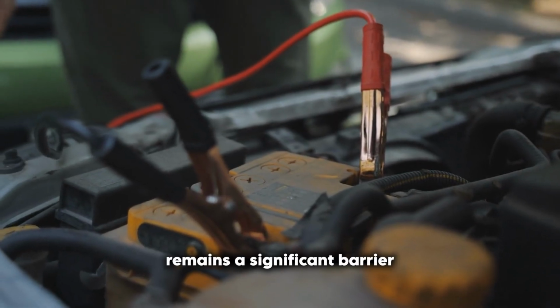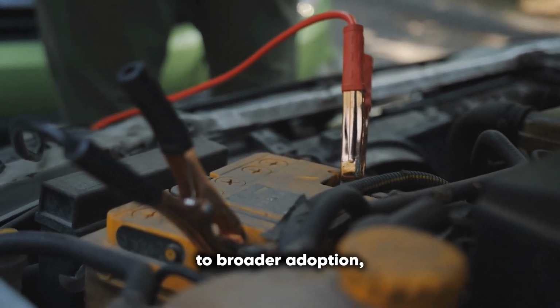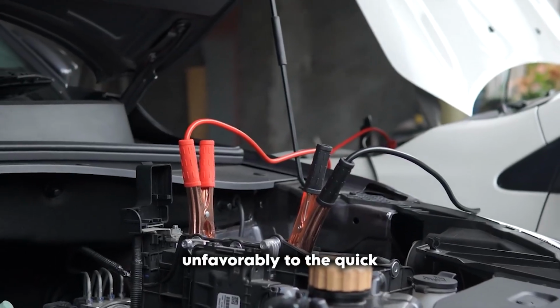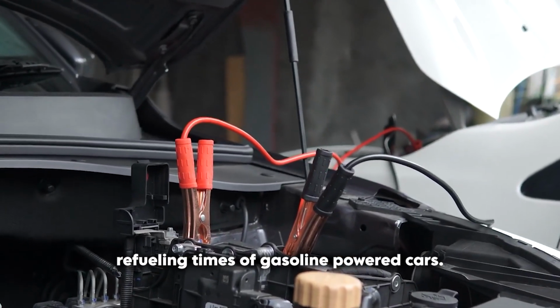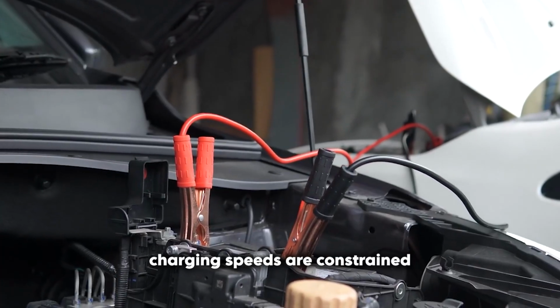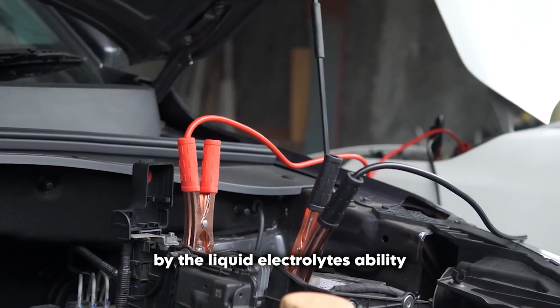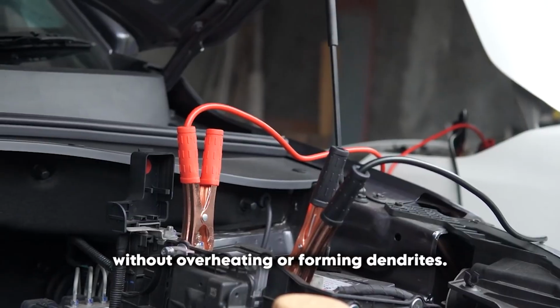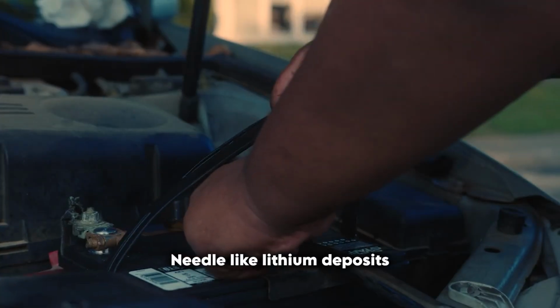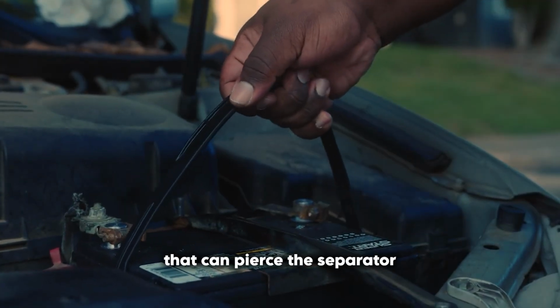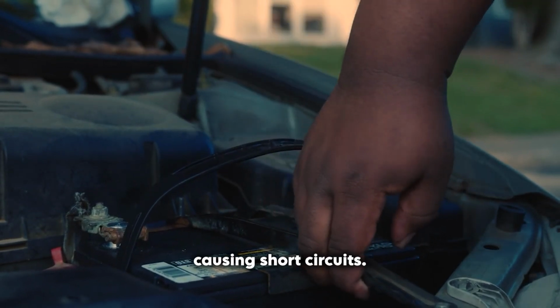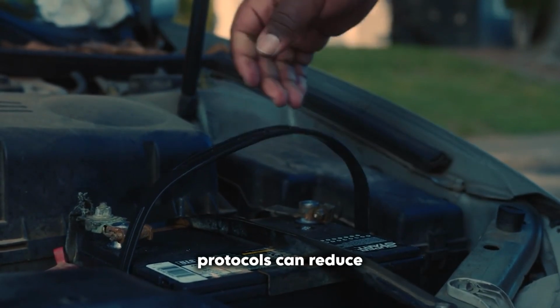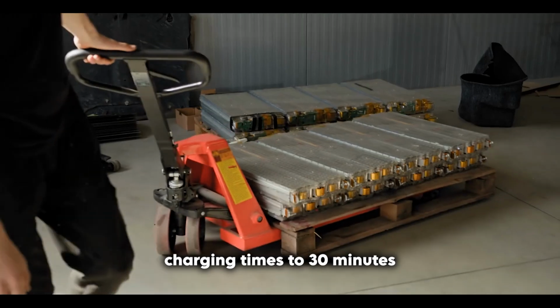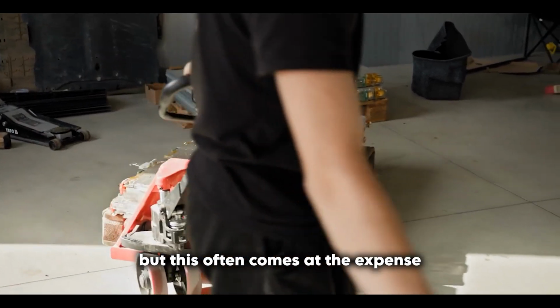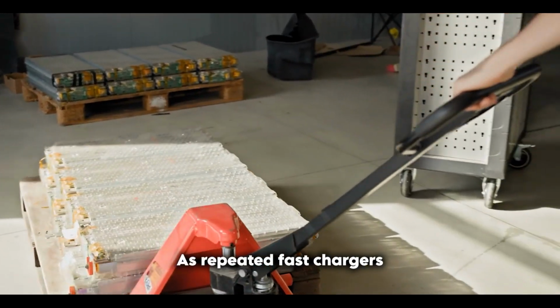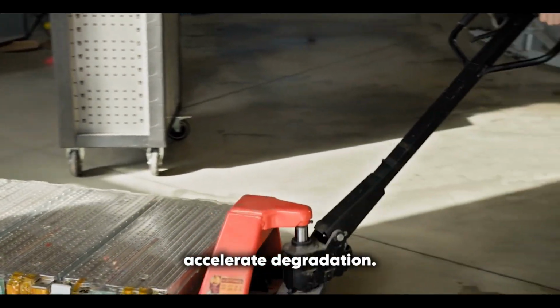This range anxiety remains a significant barrier to broader adoption, as consumers often compare it unfavorably to the quick refueling times of gasoline-powered cars. Additionally, charging speeds are constrained by the liquid electrolyte's ability to handle high currents without overheating or forming dendrites, needle-like lithium deposits that can pierce the separator between anode and cathode, causing short circuits. Fast charging protocols can reduce charging times to 30 minutes for an 80% charge, but this often comes at the expense of battery longevity, as repeated fast charges accelerate degradation.